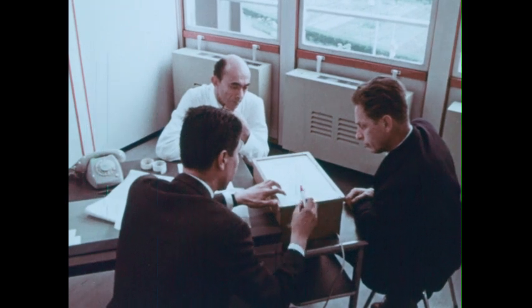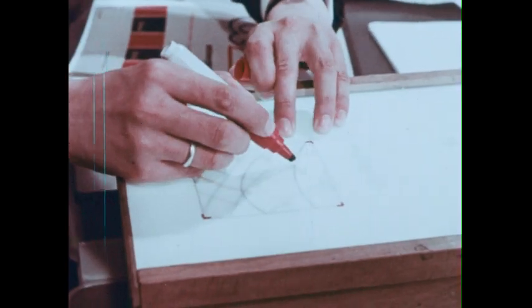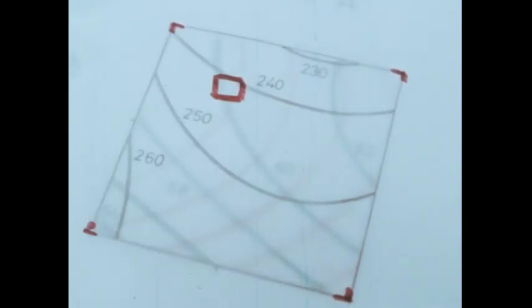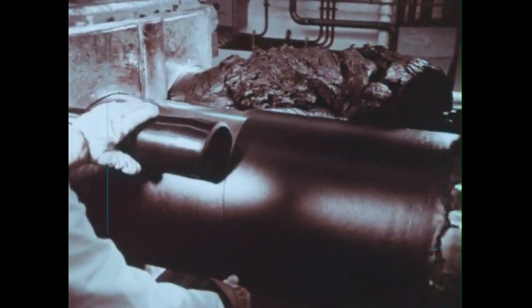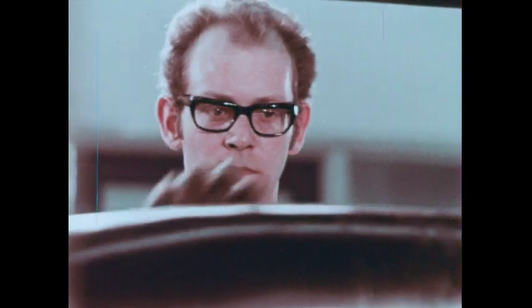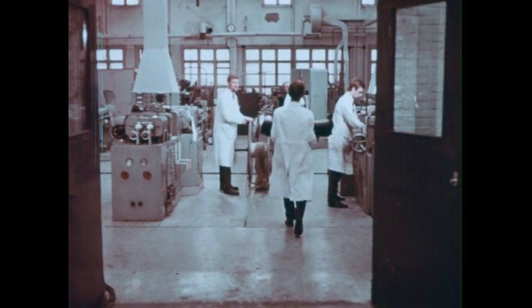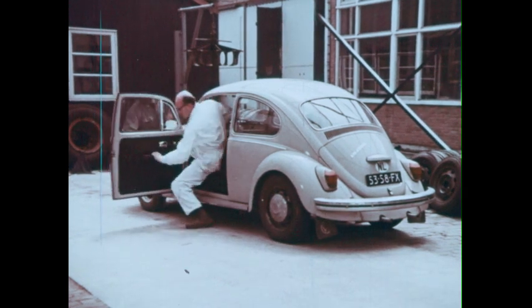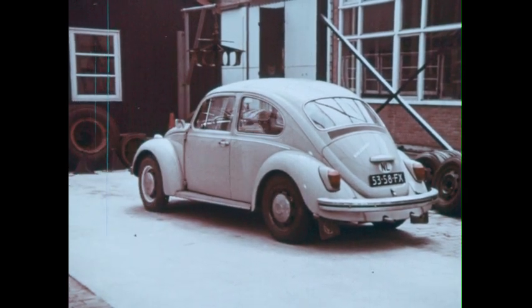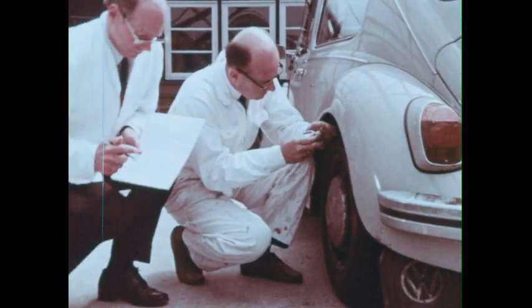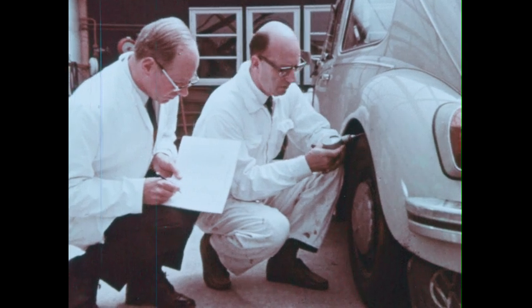Yes. Here we're looking at a compound that promised particularly good grip and wear resistance. Made from a styrene butadiene with a higher proportion of styrene than usual. Sample batches were prepared. Laboratory tests went well, and a few tires were made. Grip and wear resistance were good, but there was also a problem. Heat buildup was too high.